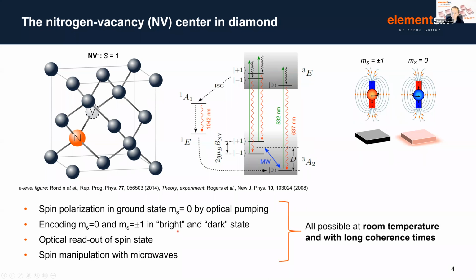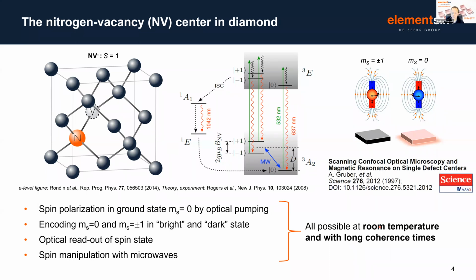And the magic of the NV center in diamond is all of this is possible at room temperature. And because of the strong tetrahedral bonding structure of diamond, we intrinsically, in pure diamond samples, obtain a long coherence time. Now, one of the reasons why this particularly gained attention in the late 1990s was that people found with very, very back then rare diamond samples, you could actually perform fundamental experiments on single NV centers. So it's like having a single atom system at your disposal, but enclosed within a nice, stable, solid state material.